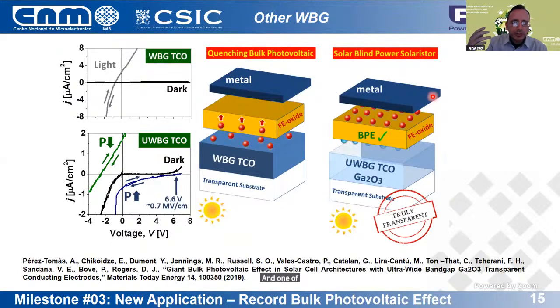One of the features which is important for optoelectronics of gallium oxide is that it's completely transparent. That means that all the solar spectrum passes through the material without any absorption. That is not the case for traditional transparent conducting oxides like zinc oxide or indium oxide or the like. And we used that concept to grow a ferroelectric and to illuminate it. And we observed that this material was a perfect platform for demonstrating the bulk photovoltaic effect, which is related to the polarization state of the ferroelectric, and traditional TCOs quench that effect.